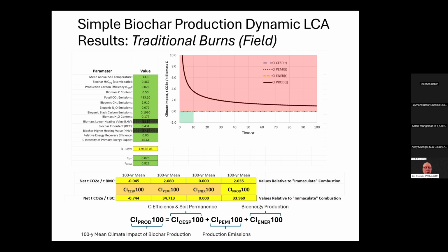But just for fun, I also throw in some numbers calculated per ton of biochar instead of per ton of biomass carbon. A lot of people tend to start with the biochar, they want to know its impact, and you can see the numbers are quite a bit larger, particularly in this case because there wasn't much biochar produced. So the same emissions per ton of biochar were quite a bit higher.